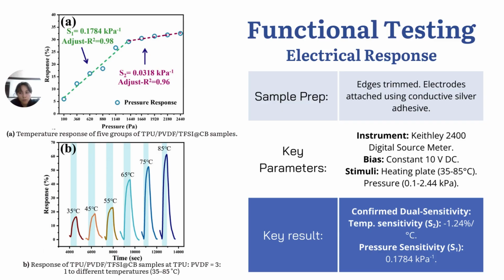The device was subjected to heating from 35 to 85 degrees Celsius and pressures from 0.1 to 2.44 kilopascals. The results confirm dual sensitivity, a temperature sensitivity of about 1.24% per degree Celsius, and a pressure sensitivity of 0.17 per kilopascal. The plots illustrate consistent stable responses across both temperature and pressure.